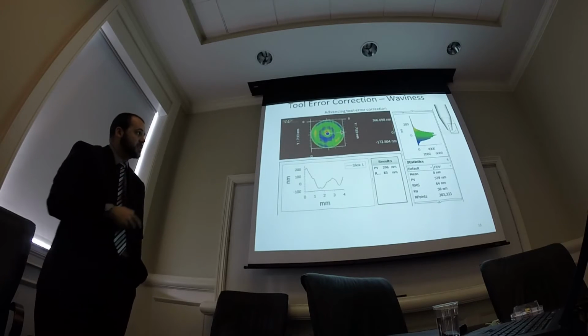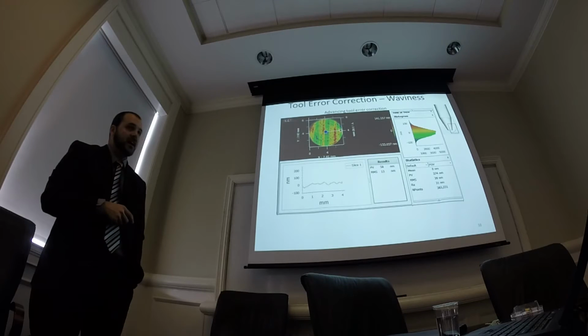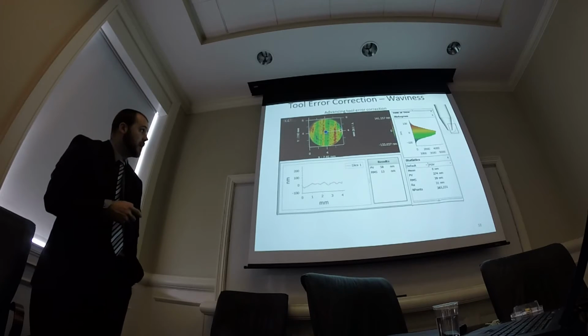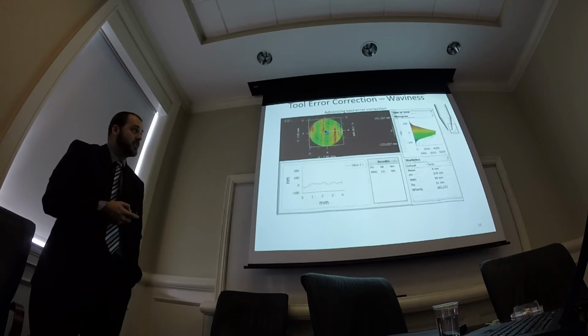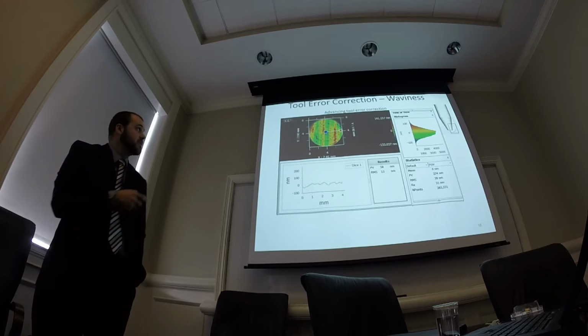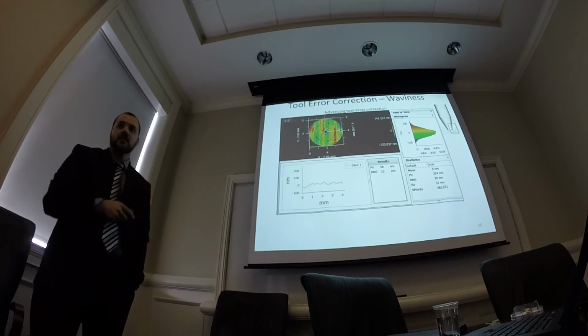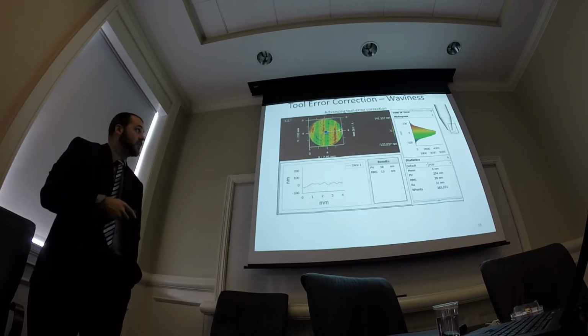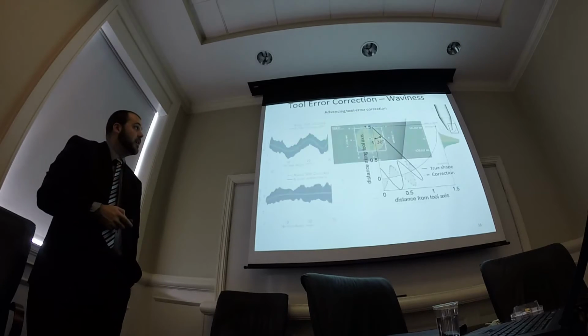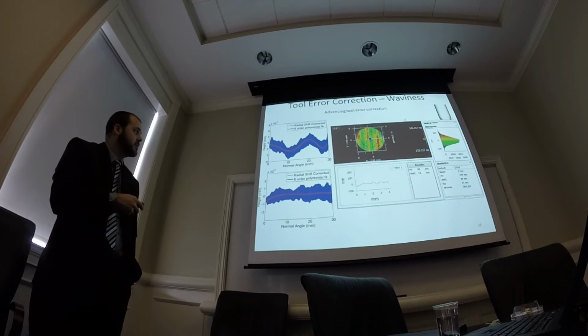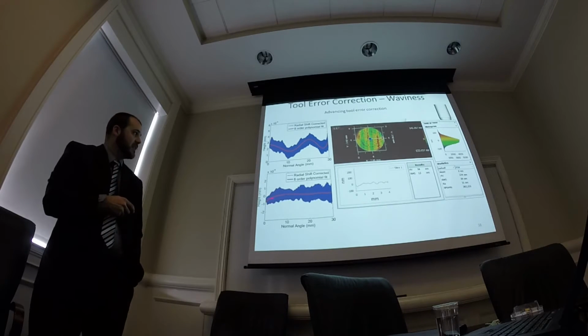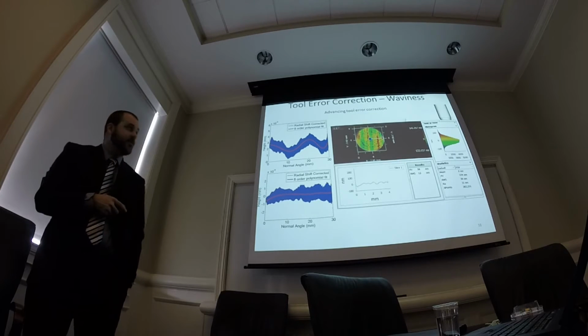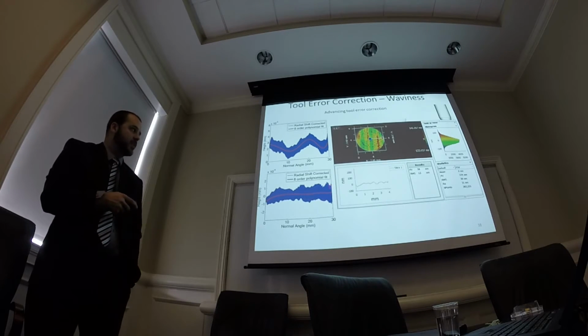So here's the original, here was after we made the correction. We went from 300 to 60 PV nanometers for the averaged, in the theta direction. So here's a MATLAB simulation of before and after. This little tail here is due to the fact that the data density near the center is much less than at the edge, so if you do a fit to this, it's much more heavily weighted at the edge.